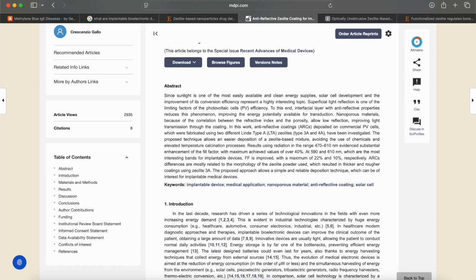Nanoporous materials, because of the correlation between the refractive index and the porosity, allow low reflection, improving light transmission through the coating. In this work, anti-reflective coatings deposited on commercial PV cells were fabricated using two different LTA zeolites, type 3A and 4A, which have been investigated. The proposed technique allows an easier deposition of a zeolite-based mixture, avoiding the use of chemicals and elevated temperature calcination processes.